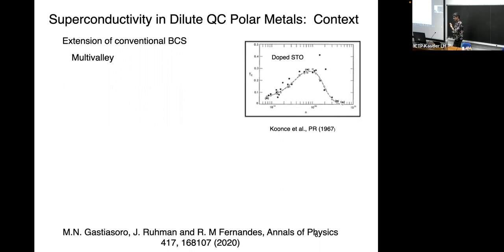Because this fit beautifully, but what happened? Well, Len Mattheiss at Bell Labs did the band structure calculation for strontium titanate. There's only one valley. So this is like the Cheshire cat with the smile. It was one of the few superconductors that was actually predicted, beautiful analytic work, very good fit with experiment, but unfortunately the main assumption is not correct. So we still have this. I don't work with theorists like that. Marvin Cohen's a pretty good theorist.